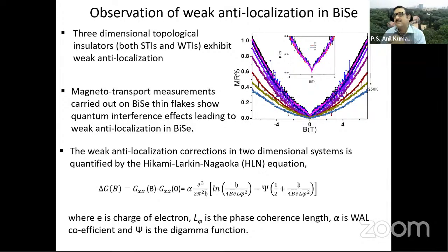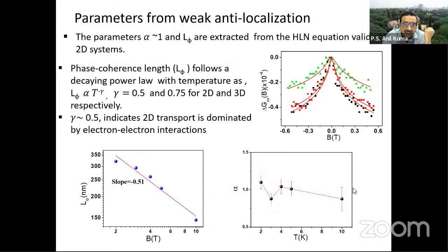Usually in a three-dimensional topological insulator, if you have a crystal with a top surface state and a bottom surface state, and you measure the weak anti-localization and look at this alpha value, it will be 1. That tells you that you have two different surface states. So we extracted the alpha value. The alpha value is approximately 1, and we can also get the coherence length from these fittings. And the coherence length we can also measure at different temperatures.